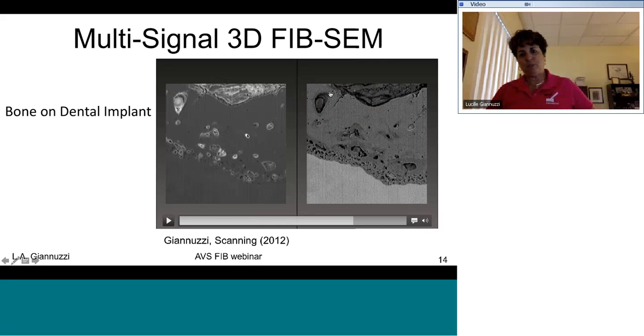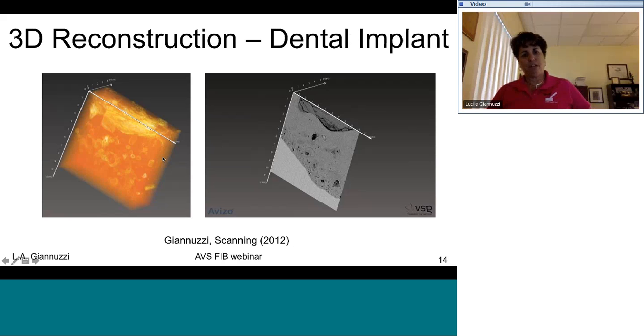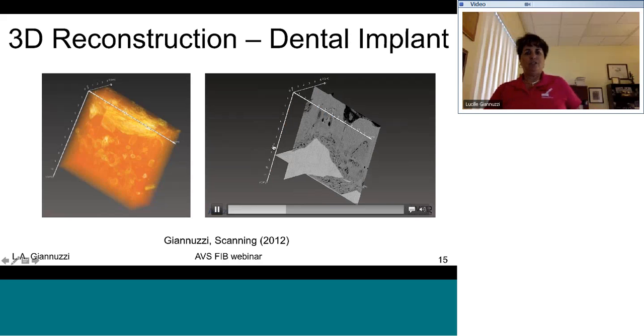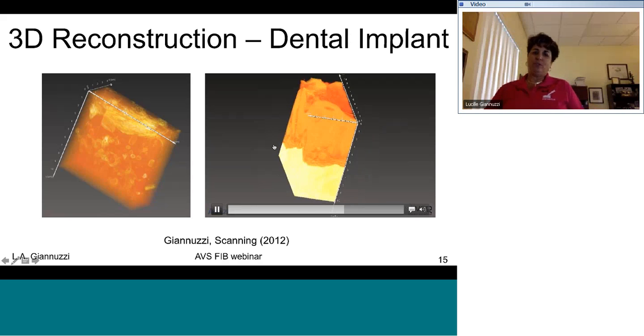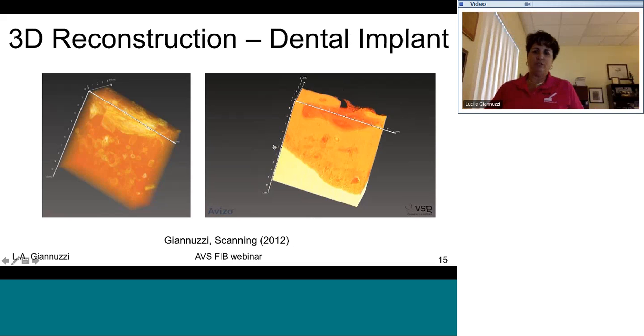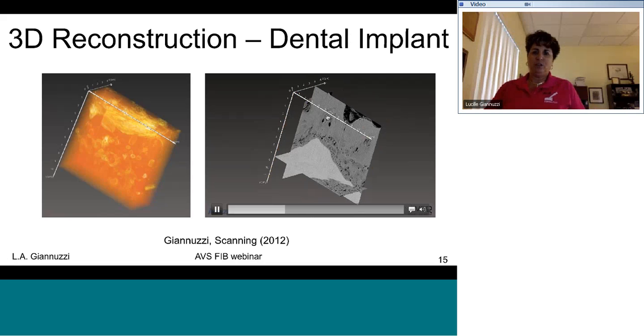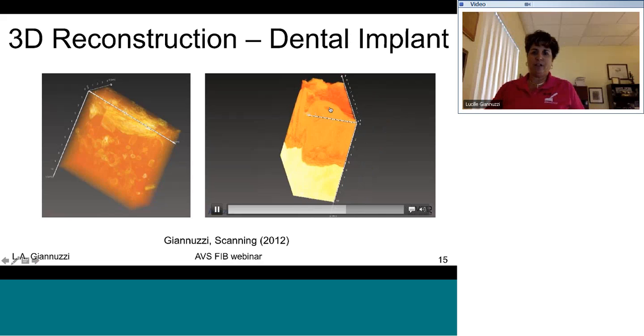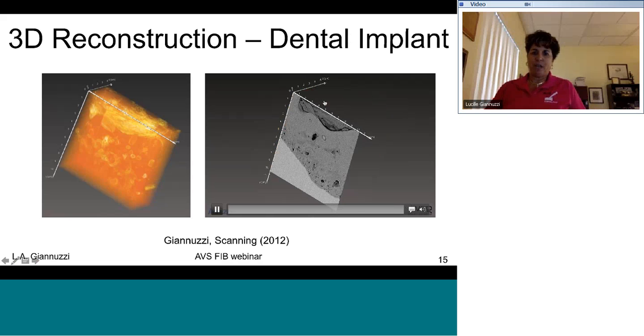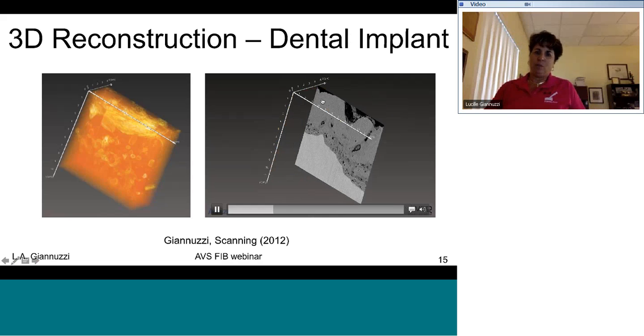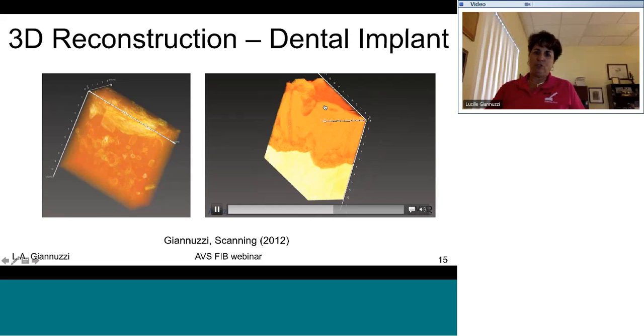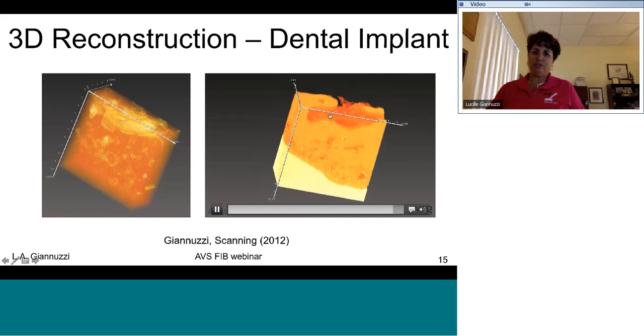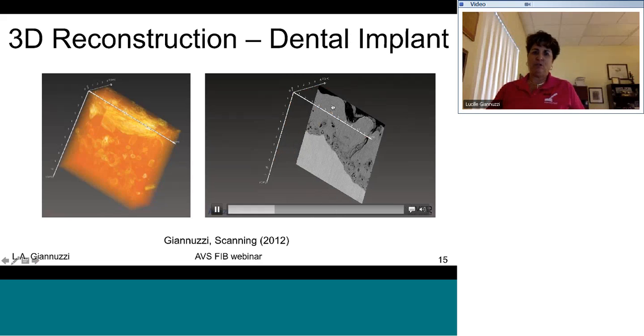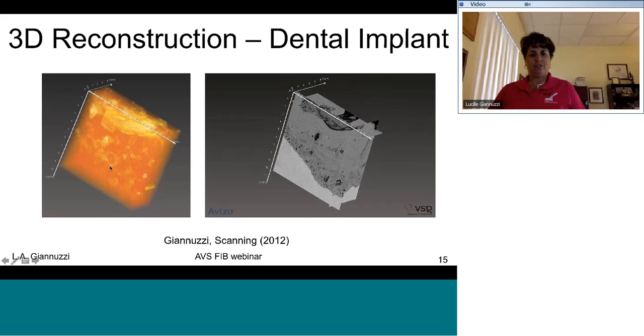But it gets below the surface because this pore is shaped like a volcano, and it actually grows down and laterally. And so now you can play, of course, games with how you reconstruct the model. You can see the pores from top down, but it is actually much smaller in diameter at the surface than it is within, and so you get bone growth actually down and into the surface as well.